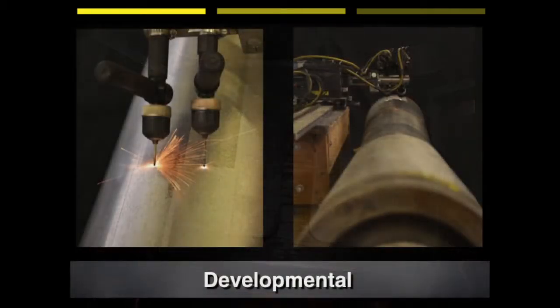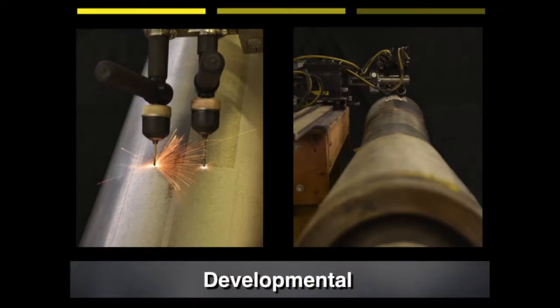Okay, that was a little look backwards in time. These applications are still being used, but we're not standing still. We continue to hunt for new applications in the aluminum mills. In the ESD world, typically, if you want a smoother ESD finish, it's a very, very slow process. Within the last 3 years, Carbinite has made great strides in both reduction of coating time and achieving smoother, more consistent finishes. We can now apply our smooth carbide coating at nearly 4 times the speed that we used to and achieve finishes all the way down to 2RA.